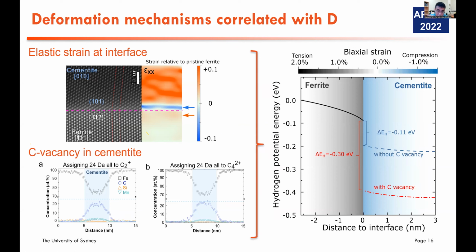So based on these two variables, we do several DFT calculations to calculate the hydrogen potential energy. And the background color here represents the strain value. When it's towards the interface, this strain is getting higher. This strain will also lead to an energy landscape that's changing between two interfaces. We also account for the existence of carbon vacancy. Without carbon vacancy, the hydrogen potential energy will be higher. If there is carbon vacancy, this energy will be much lower, and introduce a significant discrepancy between these two interfaces.